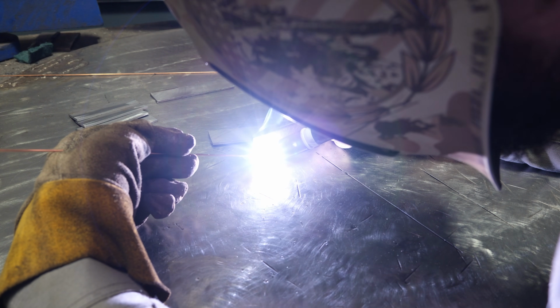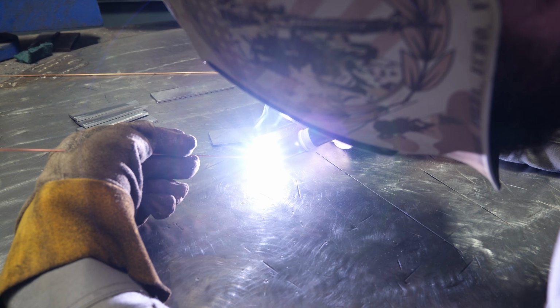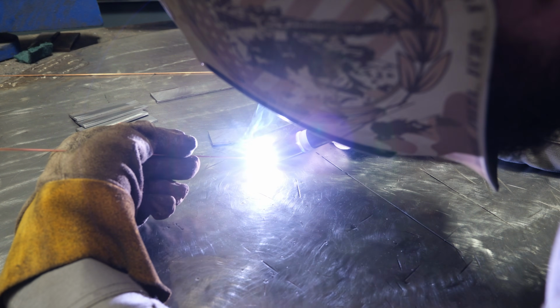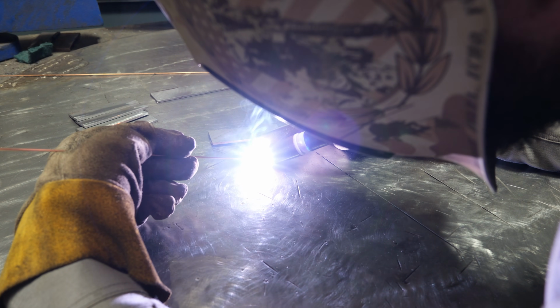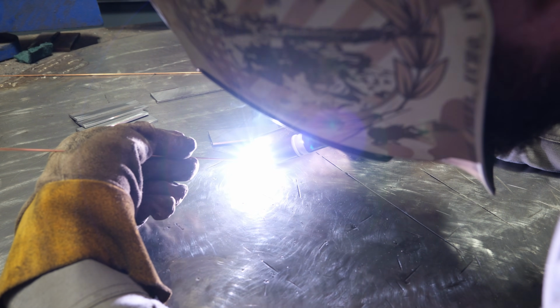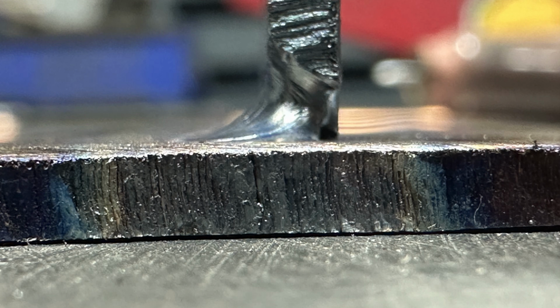Now on very thin material, you might be able to get away with this, but not on 3.2 mm, 3.5 mm and thicker, or about 1/8 and thicker. You're not going to get away with this on a fillet weld and have proper reinforcement. Here's a side shot of that weld, and you can see how the toe comes way out on the bottom plate, and it actually goes quite a bit up on the top plate. But the throat depth of that really isn't there. So simply a tighter arc and a little pinch more filler would have more or less brought the toe line in closer to the root and brought the throat depth of it, so the throat of the weld, out more.